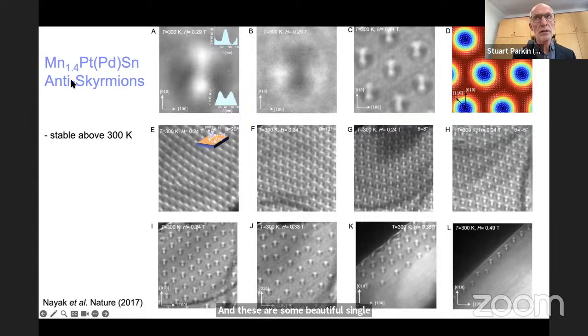It's a Heusler compound, which is normally manganese 1.4 platinum tin, but to create a stable structure, there are manganese deficiencies, and in this case, some of the platinum was replaced with palladium, about 10%. These crystals are made in Claudia Felser's group in Dresden, and we took crystals from Claudia and made these thin lamella and imaged them in our Lorentz microscope.